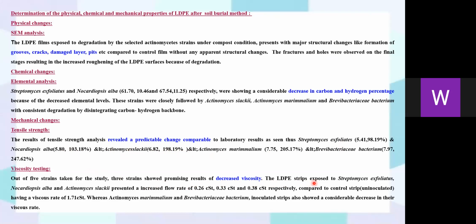LDPE strips exposed to Streptomyces exfoliatus, Nocardiopsis alba, and Actinomyces slackii present increased flow rates of 0.26 CST, 0.33 CST, and 0.38 CST respectively compared to the control, whereas Actinomyces mammalium and Brevibacteriaceae bacterium inoculated strips show a considerable decrease in their viscous rate.